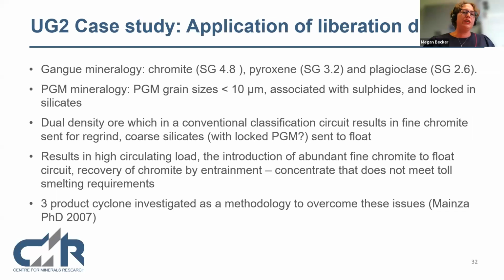So in a conventional circuit, when you have something like the dual density ore, what happens is when it goes through the cyclone, the fine chromite potentially can get sent for regrind, and it just gets ground finer and finer and finer, and you get this high circulating load. And the coarse silicate material, which potentially has locked PGM, is sent directly to the float, and those PGMs are lost. And so we land up with a high circulating load. We introduce a lot of fine chromite into the float circuit. And because there is so much chromite in that ore, I said 40 to 60%, if that chromite is recovered by entrainment, that's a lot of chromite that's been recovered. And we find that the Cr2O3 quality of that concentrate can be too high. And if you then pass it on to the smelter, they get uptight because that chromite doesn't do good stuff in the smelter.